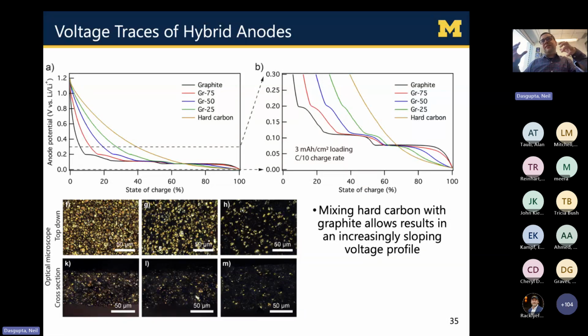So again, we went to the battery lab, mixed and blended hard carbon and graphite electrodes. Again, these are all slurry casted and tested in multi-layer pouch cells. And what we can see is that while the graphite changes color, as I showed you earlier, to gold, the hard carbon does not. So you can see now in these fully charged electrodes, the gold particles are the graphite, the non-gold particles are the hard carbon. We can see the rate and independent charging of these different particles.